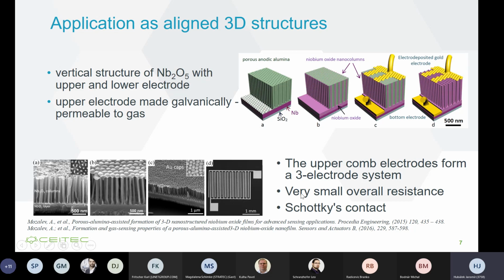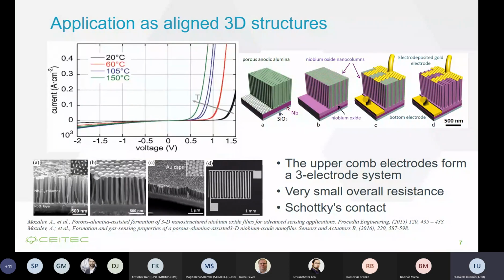A very small overall resistance is obtained by this structure. Although a single nanocolumn here has very high resistance, the overall resistance finally is very small. What was also observed was a Schottky contact. As you can see here, it can be advantageously used for the measurement method using these nanostructures.